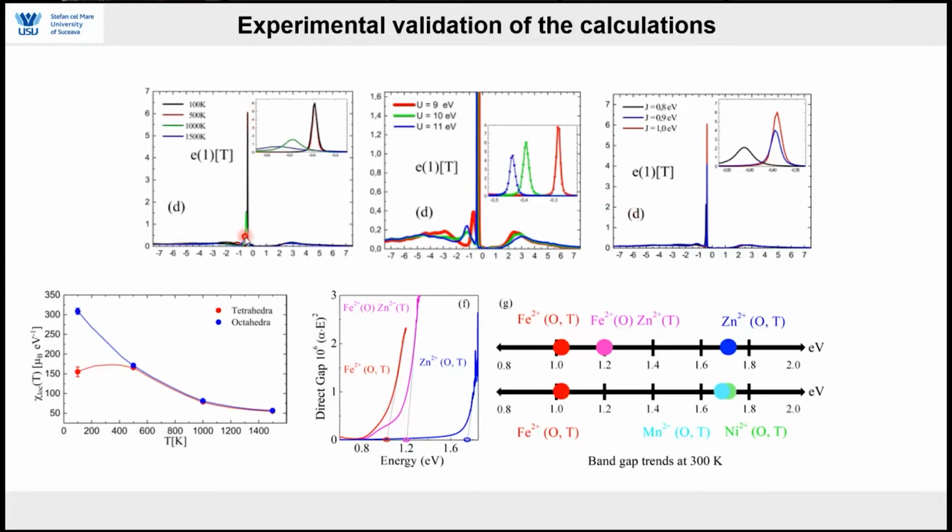Now, if you look at the magnetic susceptibility as a function of temperature, we see that for the tetrahedral side the susceptibility is decreasing as you decrease the temperature, compared to the octahedral side. This susceptibility trend combined with the temperature shows that you have something like a Kondo resonance in an insulator. This is the first observation of a Kondo-like resonance in an insulating material. You have it a lot in metallic systems, but you don't have it in insulating materials.